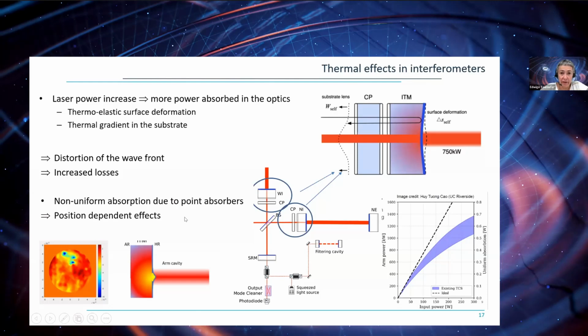This is very annoying, as this distorts the wavefront, and this increases the losses and limits the power that we can store inside the Fabry-Perot cavities, as you see here on this curve, which shows the Fabry-Perot arm power, the stored power, as a function of the input power. And you see in this blue curve that even with some thermal compensation of this effect, we are limited in the power that we can store in those cavities.